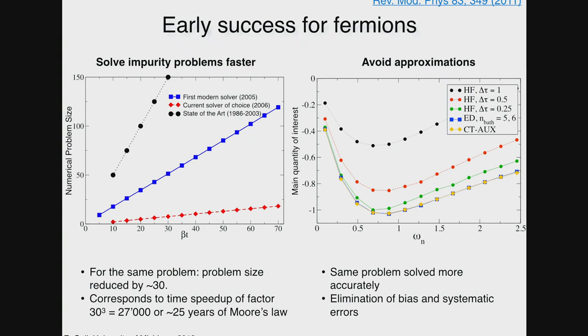Another advantage that we have is shown over here. This is an imaginary part of a self-energy as a function of frequency. You can see that if you use this method over here, you'll get something that has a systematic delta tau error. This is plotted over here. The delta tau error is controlled, so you just make your delta tau, your discretization, a little bit smaller, you'll get a different result. In this case, if you make it twice as small, you get the red curve over here. As you keep doing that, you get the green curve, and then using those 3 points, you can extrapolate to the exact result, which in this case we know from a different method, namely exact diagonalization down here.